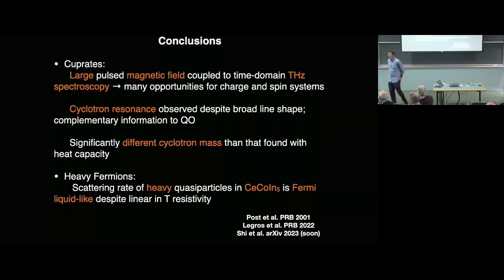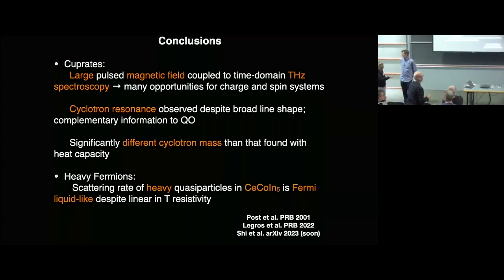Just a question which connects to what Dmitry and York was asking. If you would, at resonance, extract a different effective mass from the plasma frequency, by how much would that differ from your... Which experiment are we talking about? First part of your... Oh, in the cyclotron. Yeah, cyclotron mass. But you would, let's say, sit at the resonance and extract at the peak from the plasma frequency that effective mass, how would that differ from your cyclotron mass?